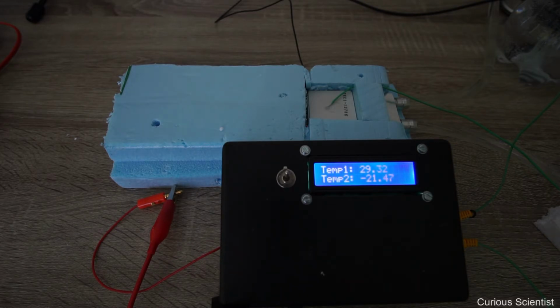And if you have noticed, then the temperature is not decreasing as it was decreasing in the beginning, despite the steps. So there you can see that the Joule heating is more and more stronger. So actually around this current, maybe if I increase the current a little bit more, then there will be a heating effect. So I will try to go up to 5 amperes and see what happens.